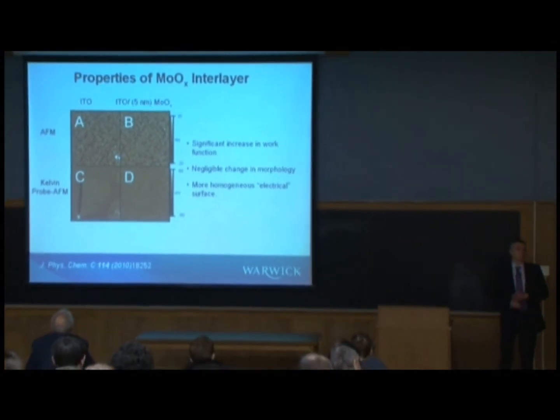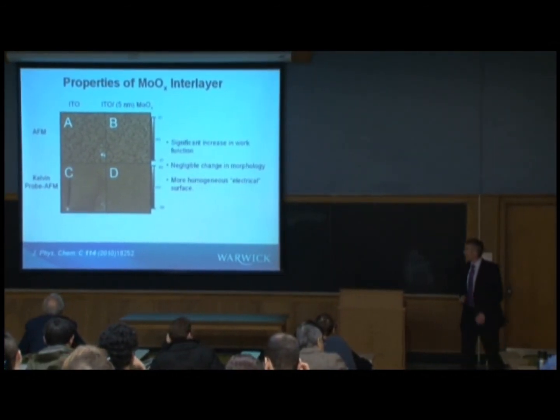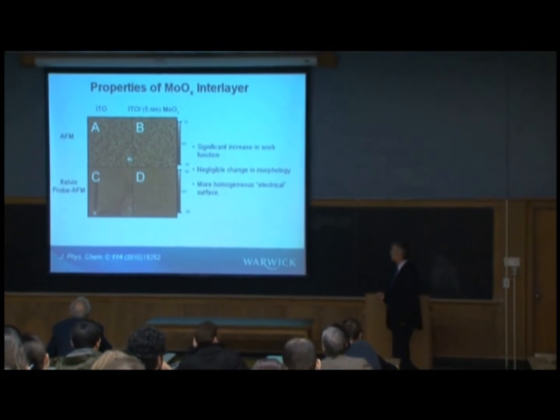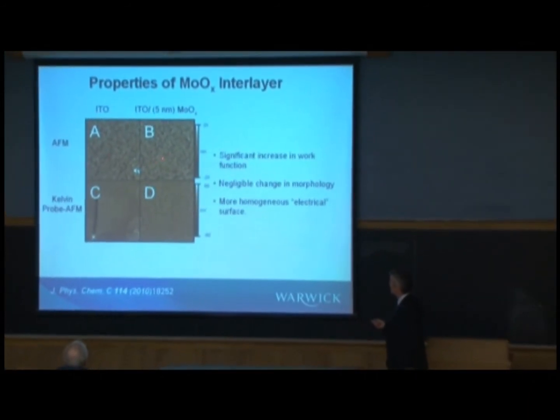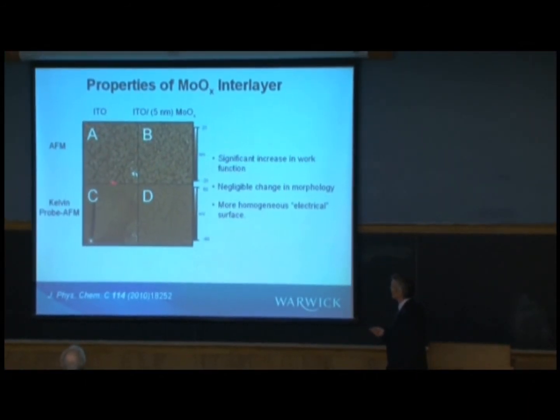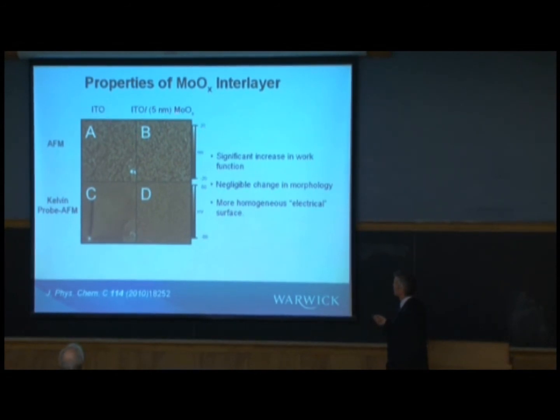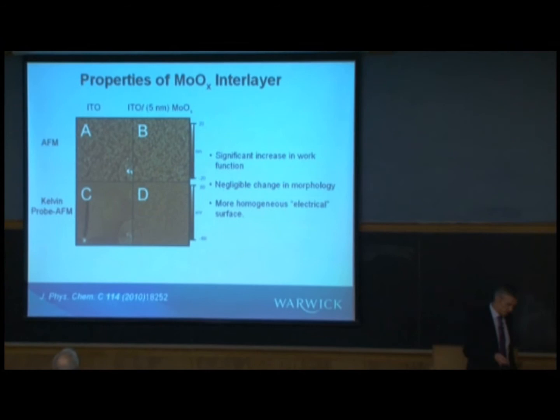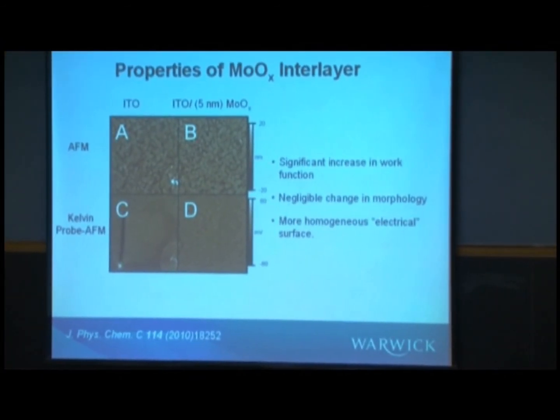So the first point, is there anything about the morphology that you're changing? And this is just showing AFM images of bare indium tin oxide and an indium tin oxide with a thin molybdenum oxide layer on top. No change. It's only a 5 nanometer layer, so morphology is not important in this regard.